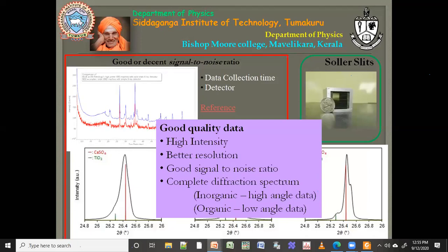There is a question from Meenu Pais. When we try to synthesize a composite sample of a metal and metal oxide, how do we distinguish whether the metal is in doped form or in composite form? If it is doped, you won't get any extra peaks. If it is not going into the structure and is just staying somewhere in your sample, then it will show as different peaks, an extra peak. I will show this again, taking the example of titanium oxide.